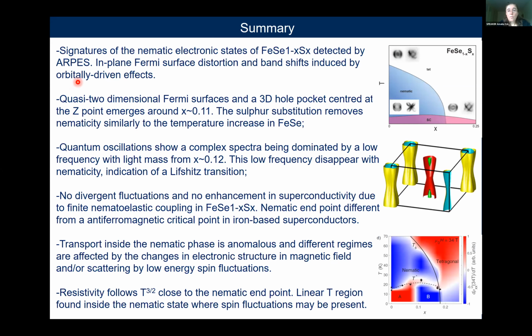Okay, to summarize, we have done lots of studies to try to understand the electronic behavior and its manifestation in this family of compounds. They are an ideal set of materials because they are clean. We can tune them, we can cleave them in situ for ARPES. They show very strong Fermi surface distortion and band shifts because of the nematic orbitally dependent effects. We have small changes and the presence of a new little three-dimensional pocket, which seems to be important for transport behavior in this multi-band system. And there are no divergent fluctuations at the nematic endpoint, suggesting that something else suppresses both this fluctuation and superconductivity, and one of the potential reasons could be the magnetoelastic coupling.